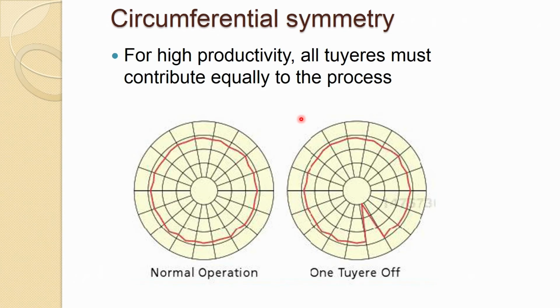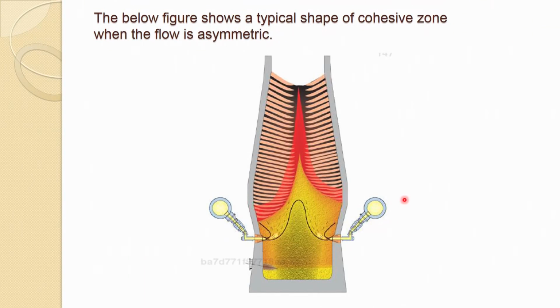Another one is about the circumferential symmetry. This is one important one again. For high productivity, all tuyeres must contribute equally to the process. This figure shows one normal operation where all the tuyeres are operating, and you can see a very good circumferential symmetry in all respects. Now, in this figure, one tuyere is off, and suddenly you can see the imbalance over here. That is the tuyere which is off. That is giving quite an uneven circumferential symmetry, and that is going to create quite a bit of problem.